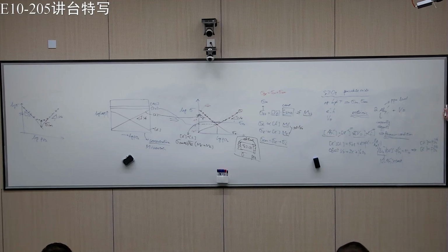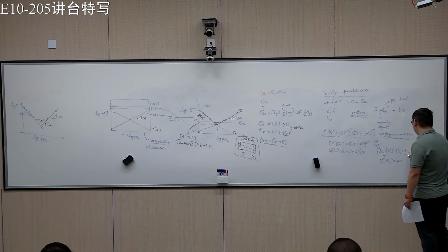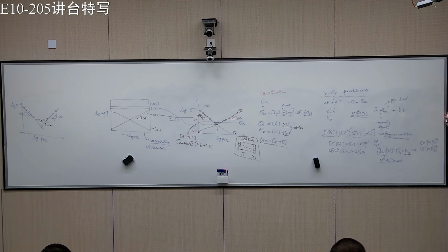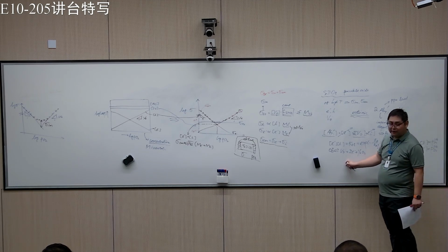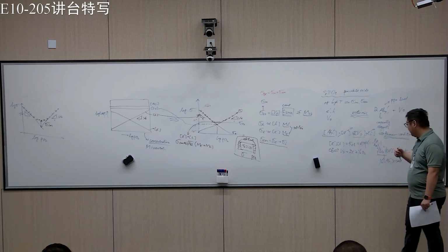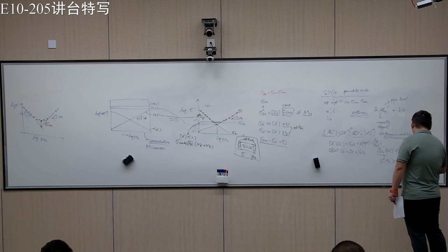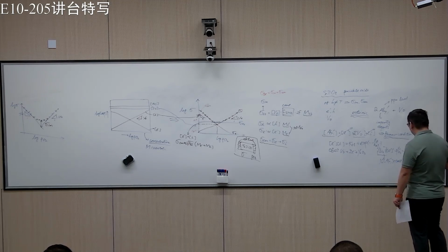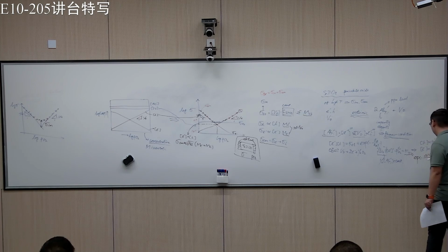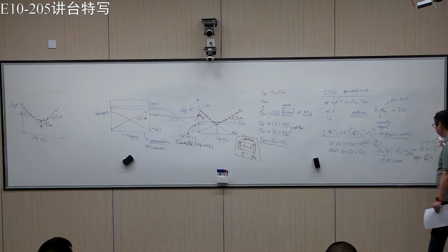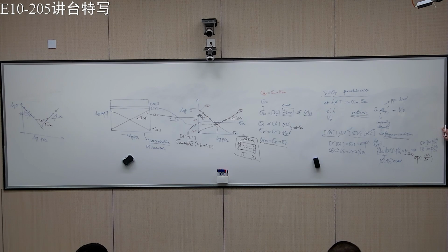So if you change the temperature, you again go somewhere over here. Remember that this is the chemical equilibrium constant for this chemical reaction, basically forming the oxygen vacancy. So this will be some kind of exponential of minus delta H. Let's just write H, because you can ignore the entropic term. Actually, because it can cost energy, right?